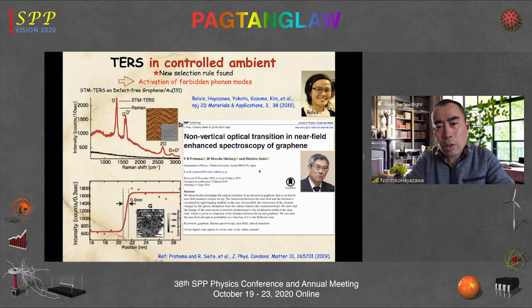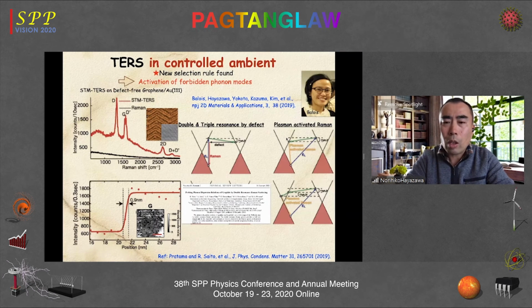Based on the fruitful discussion with Professor Riichiro Saito in Tohoku University, who is a very famous and active professor in the field of theory on graphene carbon-related materials, recently Saito Sensei published a unique theoretical paper, entitled Non-Vertical Optical Transition in Near-Field Enhanced Spectroscopy of Graphene. Today I do not have much time to introduce the details of this work, but the point is that because of the highly confined electric field, you can achieve very high wave number from the enhanced electric field, which compensates the momentum mismatch in the electron-hole pair recombination or the Raman process, so that the forbidden D band is now activated by our tip-enhanced Raman spectroscopy with 1 nanometer spatial resolution without the defect.